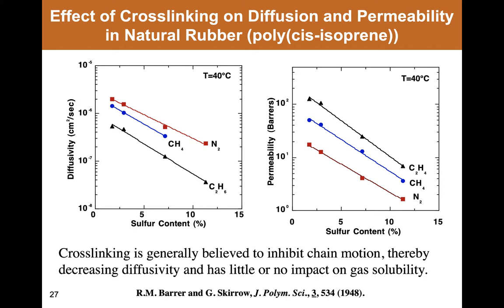It is a cross-linked material, and so the effect of cross-linking is important, and at least in the tire application, it's also loaded with carbon black nanofillers, and so the transport through the wall of your car tire is transport through a heterogeneous material that can be modeled using some of the models that we just discussed in the last few slides. The traditional way that natural rubber or polycis-isoprene would be cross-linked is by mixing it with sulfur and then heating it. This is the process that Goodyear used to first make rubber for car tires nearly two centuries ago.